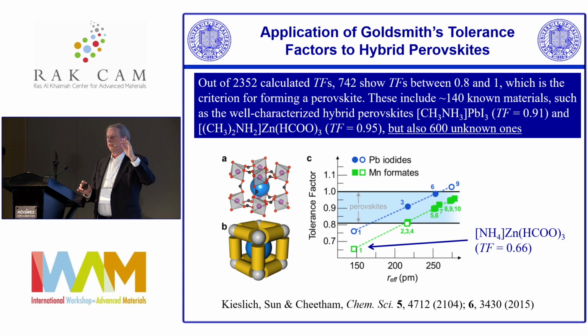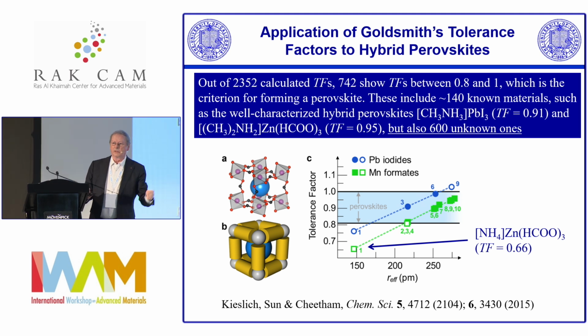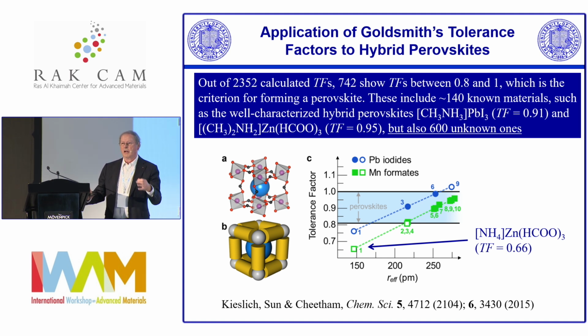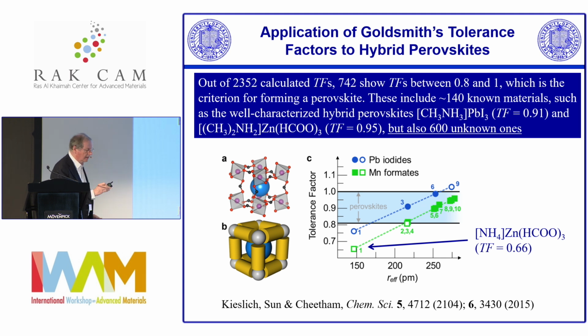It's not the only descriptor for perovskites. Satisfying this is a necessary, but not always a sufficient condition to get a perovskite. And we've done a lot of work. There's a poster by Greg Kent this afternoon where he showed that we've been able to make double perovskite iodides in Santa Barbara, which have never been properly made and characterized before. And we realized a couple of years ago, working with Pratap Vishnoi when he was in Santa Barbara, that for a double perovskite you also have to worry about whether the trivalent cation is big enough to support octahedral coordination. And that's not covered by the tolerance factor. So for systems like the iodides, that's an additional descriptor that has to be satisfied.